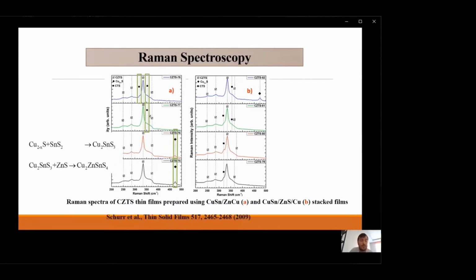According again to this formula, you can see the copper tin sulfide phase occurs in these samples. It means that for E-type samples, maybe the sulfurization temperature is not enough. So maybe we should extend the sulfurization temperature to obtain a fully CZTS structure.